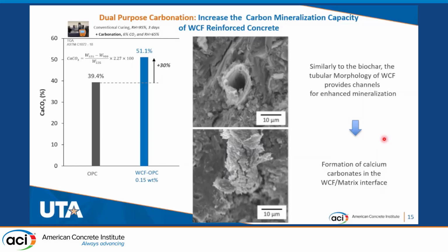the fiber-reinforced concrete after carbonation. Also we observed here from the TGA results on the left part that the mineralization capacity of the fiber-reinforced concrete is increased by 30% compared to the OPC. And the SEM imaging revealed actually a similarity with biochar. The waste cellulose fibers, due to their tubular morphology, can also provide channels where the mineralization preferentially takes place at the interface between the fiber and matrix, and also inside the hollow structure of the fibers.